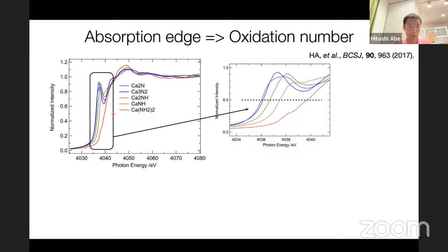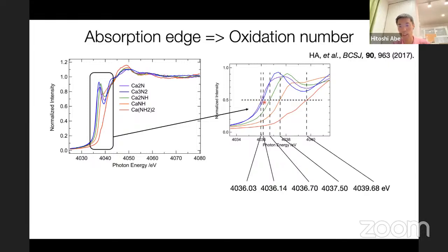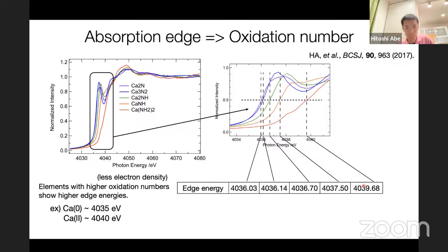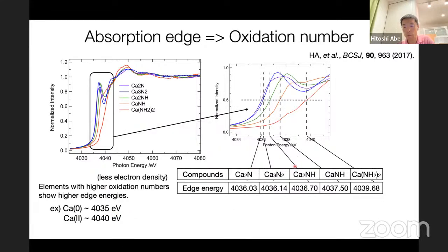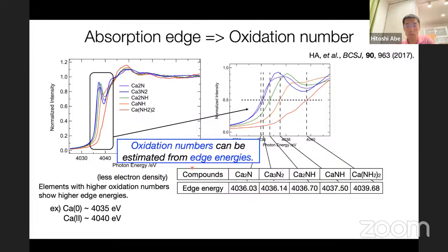Here is the enlarged image of the absorption edge of the calcium K-edge XANES spectra, and we read the edge energy from these spectra, like 4036.03 eV, 4036.14 eV, and the like. So as I said before, elements with higher oxidation numbers show higher edge energies. For example, metal calcium will show the edge position at 4035 electron volts, and calcium 2+ shows 4040 electron volts. And these compounds show these absorption edge energy positions, and oxidation numbers can be estimated from these edge energies.